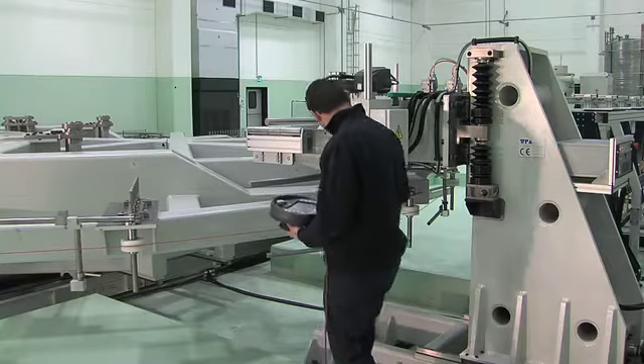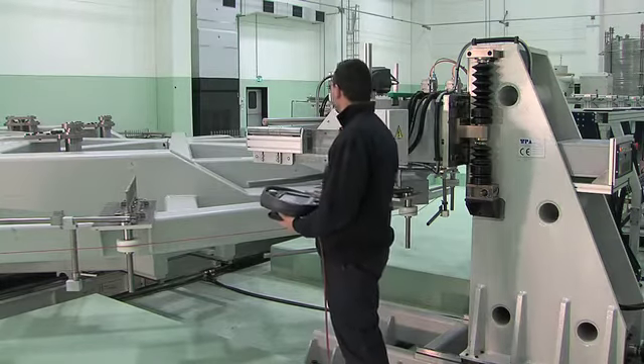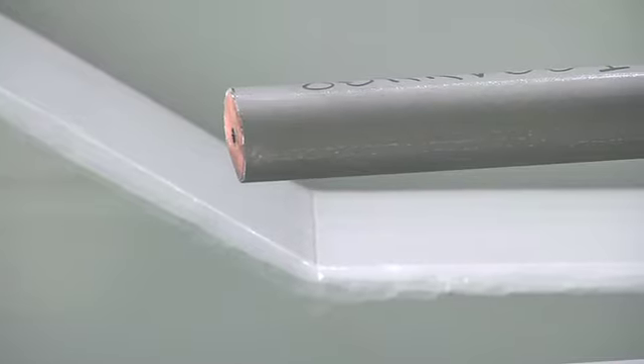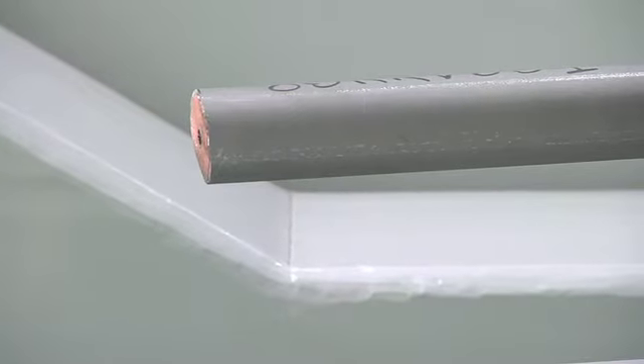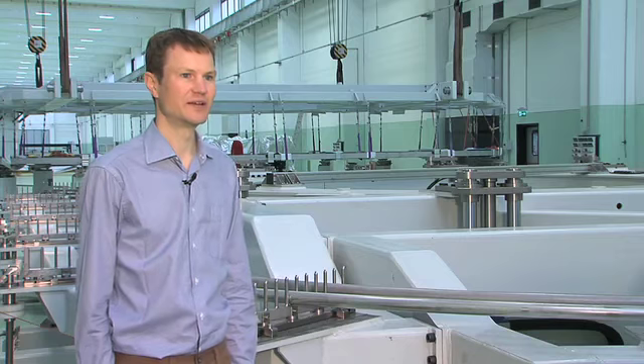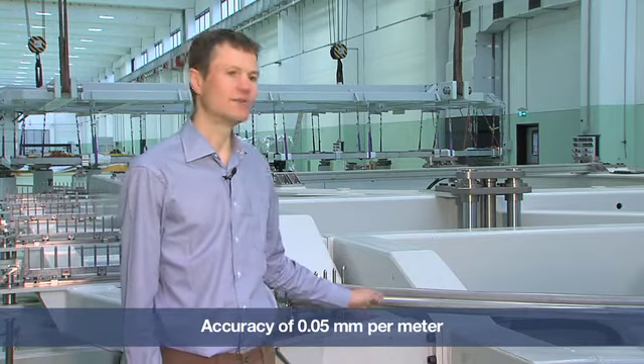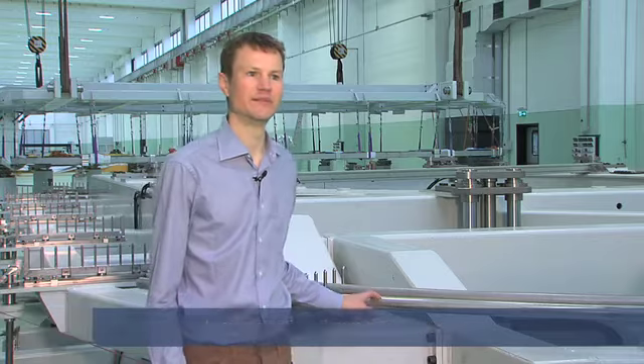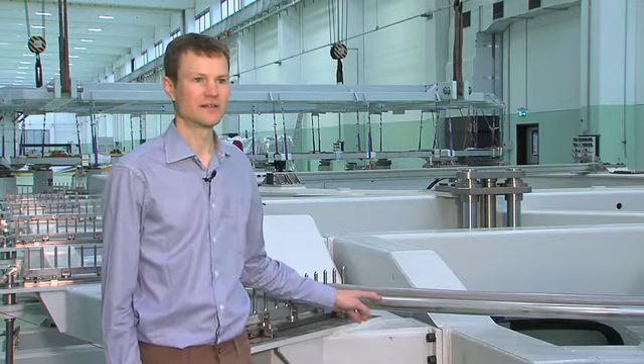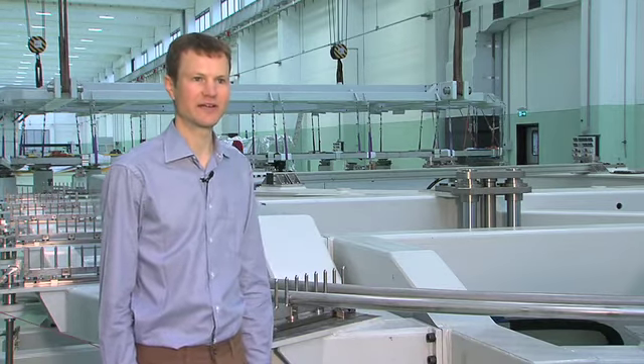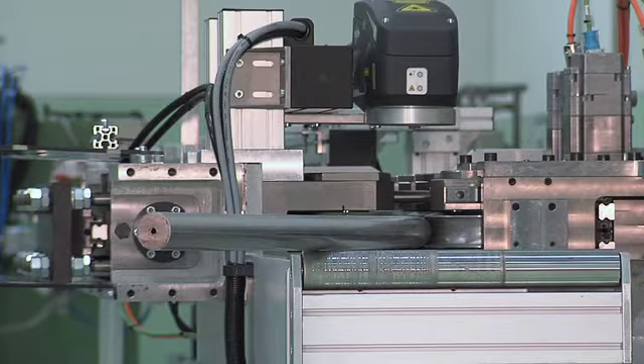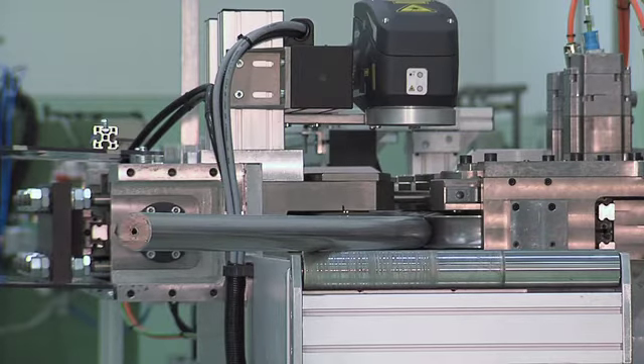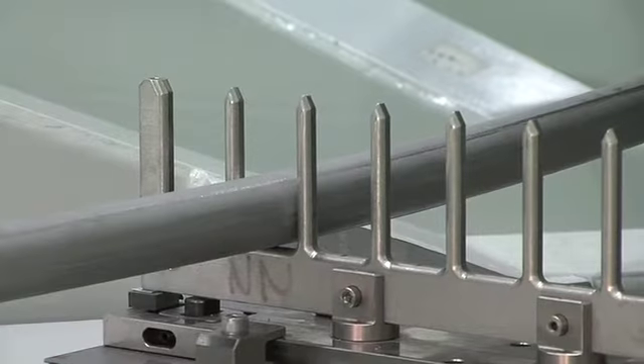What's challenging about the work being undertaken? Well, above all else, extreme levels of accuracy are required. For instance, we need to control the length of the conductor during bending to an accuracy of around 0.05 of a millimeter per meter. To do this, laser systems are used to determine the correct length of the conductor for each turn. As its length changes during bending, we measure the conductor both before and after in order to compensate for this and to achieve the correct length in the end.